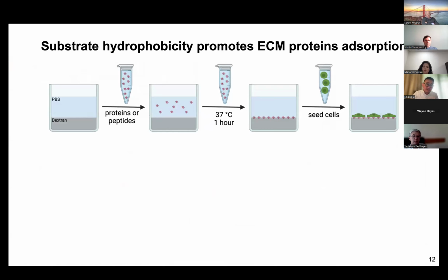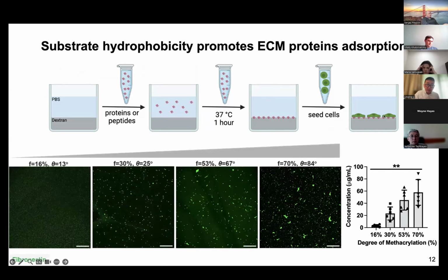The flow is that we have the protein in solution and incubate at 37 degrees. We hypothesized that with hydrophobic surfaces, we can adsorb and pull down the ECM protein onto the surfaces, and these ECM proteins can then promote cell adhesion. The first thing we did was use fibronectin as a model protein and look at how the ECM proteins can be adsorbed on the surfaces.